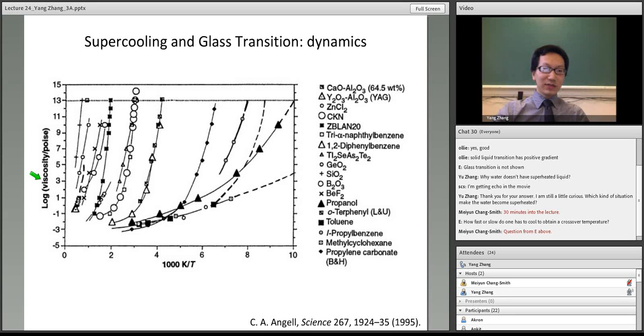So this figure summarizes around 20 glass-forming liquids. Some of them are molecular, some of them are organic, inorganic, metals. So you can see that although the glass transition temperature is different, the glass transition temperature is almost uniquely defined as when the viscosity reaches 10 to the 13 poise. As physicists, we always want to try to find the universality between different materials, just like the universality or scaling laws near the critical point. For the same reason, we want to find some universal scaling behavior of all the viscosities.